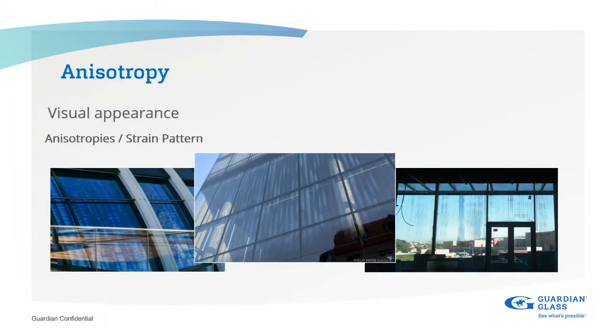Anisotropies. As I mentioned earlier, the anisotropy is more apparent in the thicker glasses. It can be seen easily in 6 mm glasses as well. Usually this is more apparent when you view it at an angle under polarized light.